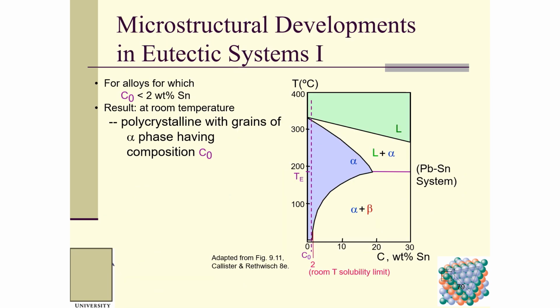So microstructure development in eutectic system. For alloys for which the composition is less than 2% of Sn, the result at room temperature is polycrystalline with grains of alpha phase having composition of C0. So polycrystalline with alpha grains. You can see we have alpha here. This is solid. So this is polycrystalline, these are the grains, polygrains.